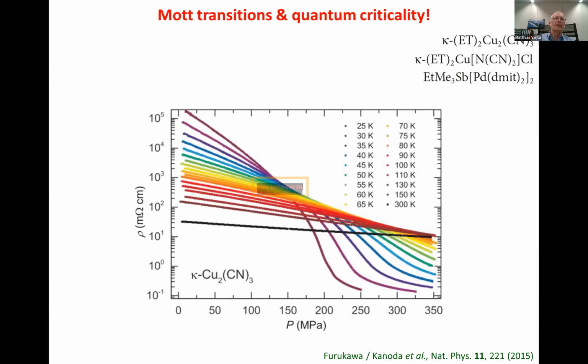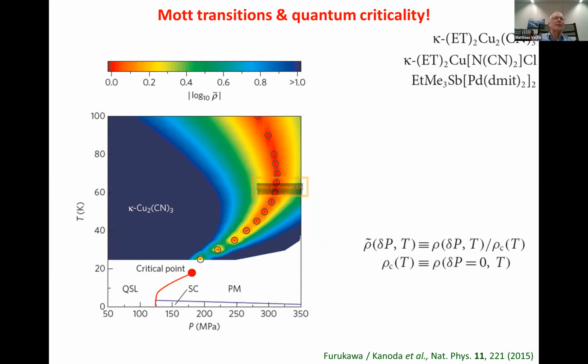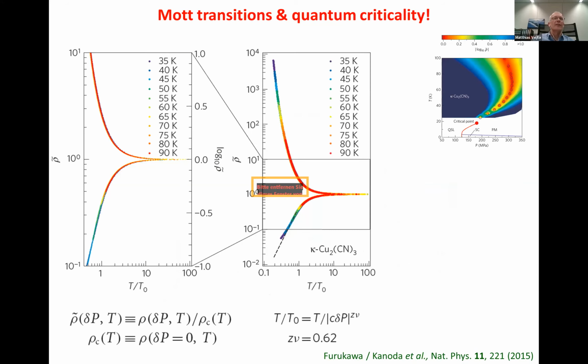But then the group of Kanoda actually tried to verify this prediction experimentally on a number of organic compounds, listed here on this slide. Again, these are all tunable by pressure. You see resistivity curves as a function of pressure, which you can plot in this phase diagram, and you can do the same scaling procedure to get a beautiful data collapse.